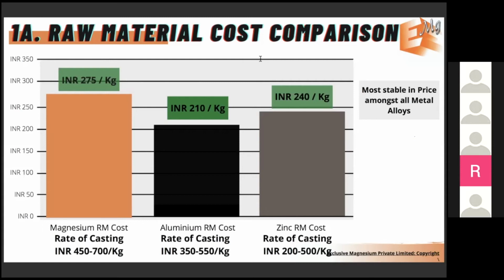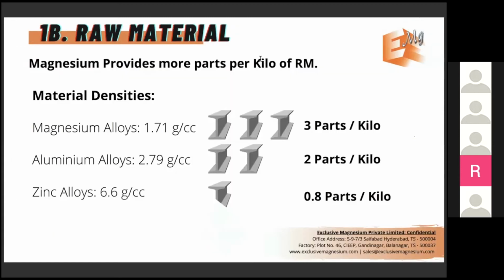So that's one aspect. In terms of production, if you take 1 kilo, there's a part with 1 kilo of magnesium, you are able to make three parts. What that density difference really means is that with aluminum you are making about only two parts, and with zinc you are making less than a part, right? So that's just how much better raw material can be used.